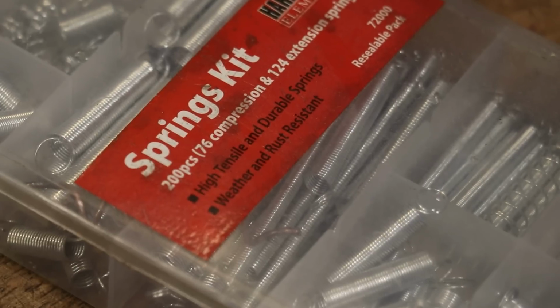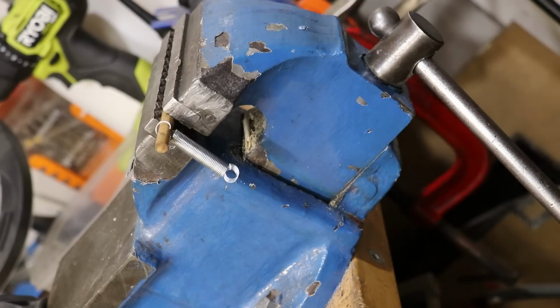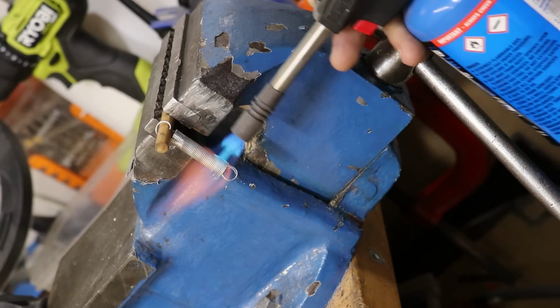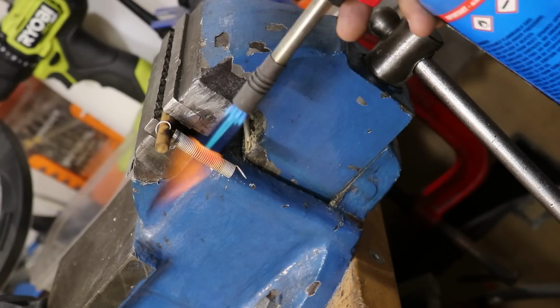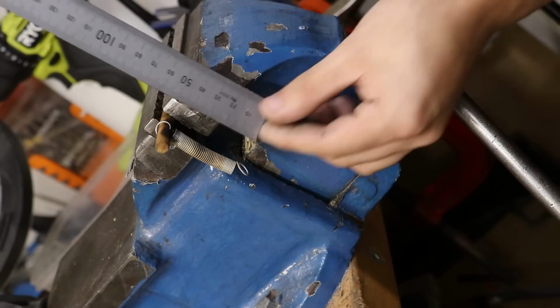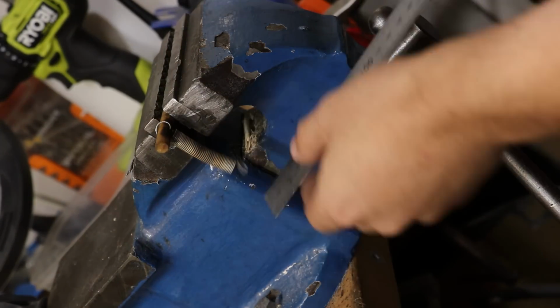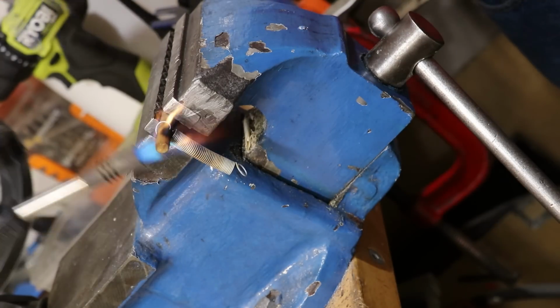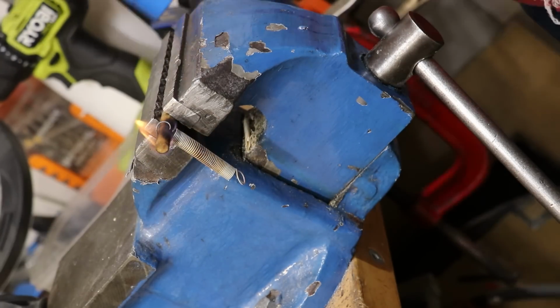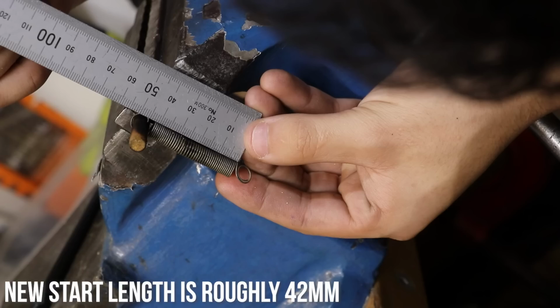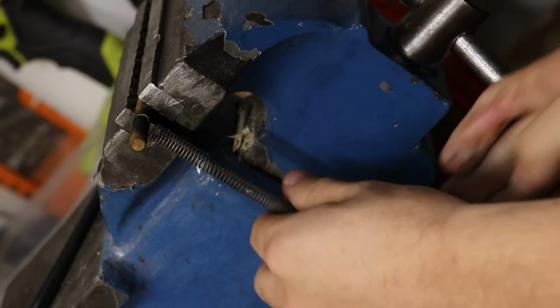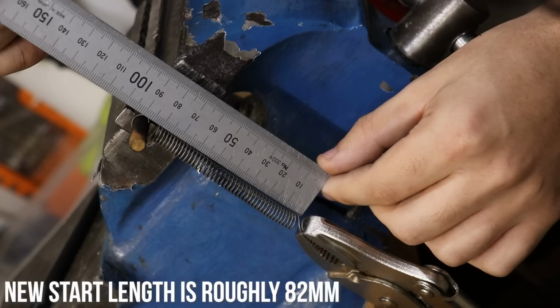Now the spring is made from tempered steel, so let's go ahead and normalize it. I'll heat it up with a blowtorch, which should soften it. Effectively, we're doing the exact opposite to what we did last week. Unfortunately, with it being hardened steel and a coiled up spring, we are going to see some relaxing of stresses, and it won't be 100% the same length as it was beforehand. After letting it cool, it's now grown ever so slightly to about 40 millimeters. However, once I put the vice grips on, it drops to 80 mil. The displacement is the same, 40 millimeters.